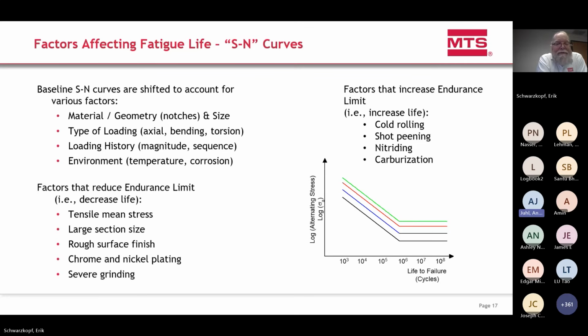Things that decrease the life, making these curves lower, include a tensile mean stress, a larger section (which would have more defects in it), a rough surface finish, or a hard surface finish that cracks and causes a notch, or maybe severe grinding of the surface. So these S-N curves move based upon these parameters.